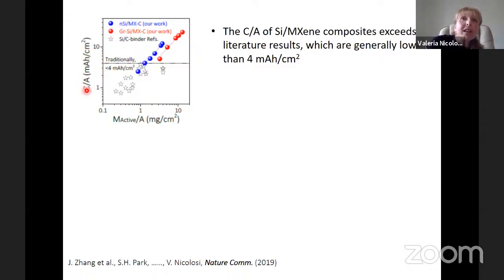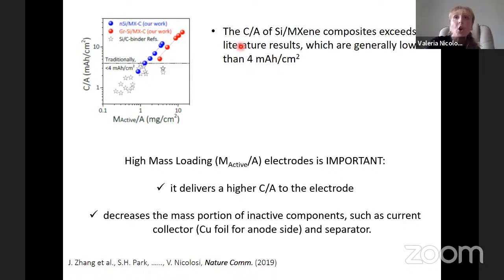If you look at the areal capacity here as a function of the mass of the active material, this horizontal line is really where traditional commercial batteries stand. So you can reach a maximum of about 4 milliamp hours per square centimeter, while we could go well beyond and above that. So this is where we see that this material is really working well. So we deliver high areal capacity to the electrode, and also because we can achieve very high mass loading of silicon, which is the anodic material, we can decrease the portion of inactive components, such as the current collector, the separator, and things.